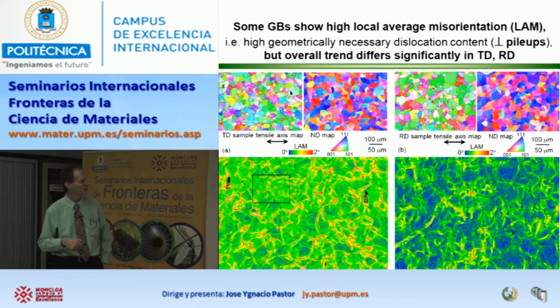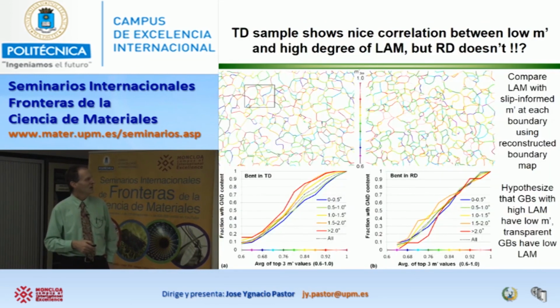And there seem to be more evenly spread out hot spots where there's lots of dislocation pileups, and maybe not so common over here. So there's a big difference. So if we work out what this M prime parameter would be with a color scale, M prime goes from 0.6 to 1 here. The darker purple is 1 and blue is lower.